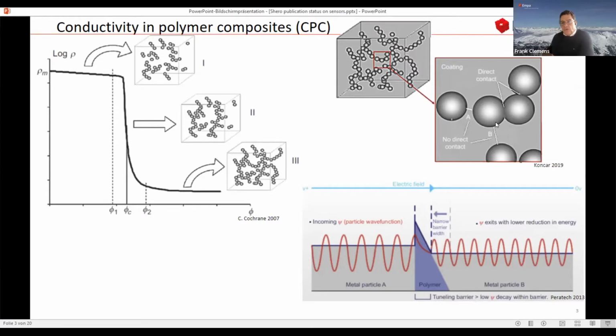The main difference between hopping of the electron from one conductive particle to another and the tunneling effect is the energy level, which you can see underneath here. If we have a hopping effect, the electron has to have so much kinetic energy that it really can jump from one conductive particle to the other. In the tunneling effect, the distance is normally smaller, and the idea is that we have this wave function. If we have a barrier here which is not conductive, then even without that high energy the electrons can still move to the other particle, and by this generate electrical conductivity even though the particles are not completely together.